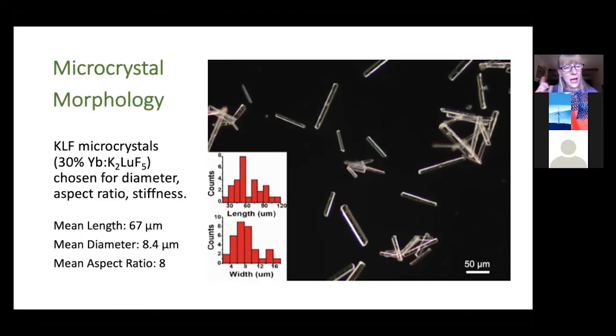So again, keep in mind that average diameter of about 8.4 microns and that length over 50 microns. So notice here the 50 micron scale for these crystals. A lot of these crystals are separated individual, but there are some that grew together. They're hard linked, and that resulted in some misalignment. But you'll see with the individual crystals, we were able to achieve excellent alignment.